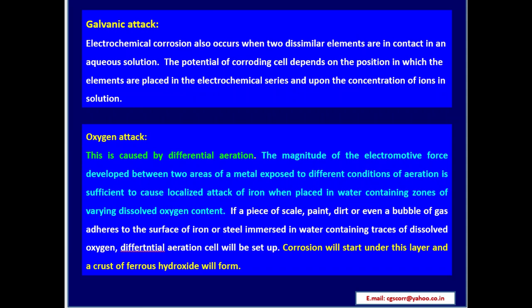Galvanic attack. Electrochemical corrosion also occurs when two dissimilar elements are in contact in an aqueous solution. The potential of the corroding cell depends on the position in which the elements are placed in the electrochemical series and upon the concentration of ions in the solution. Oxygen attack. This is caused by differential aeration. The magnitude of the electromotive force developed between the two areas of the metal exposed to different conditions of aeration is sufficient to cause localized attack of iron when placed in water containing zones of varying dissolved oxygen content.